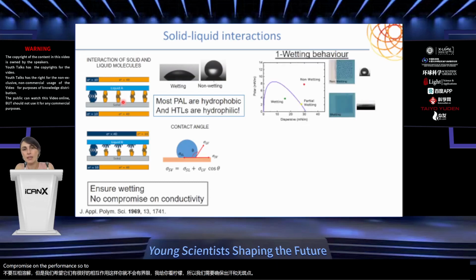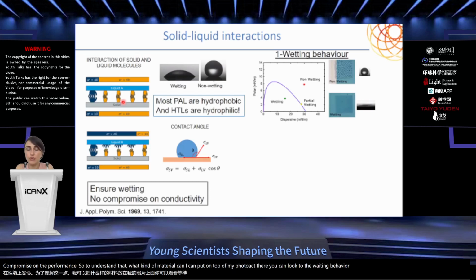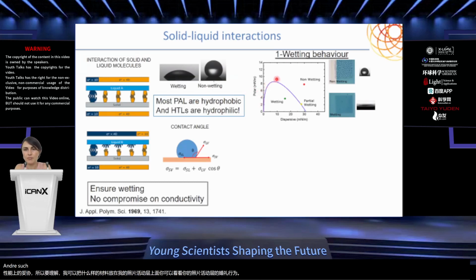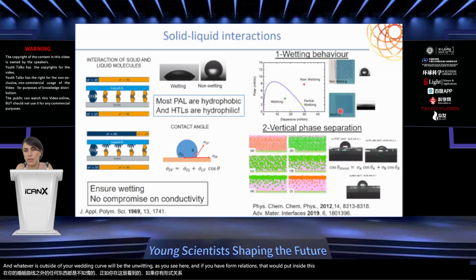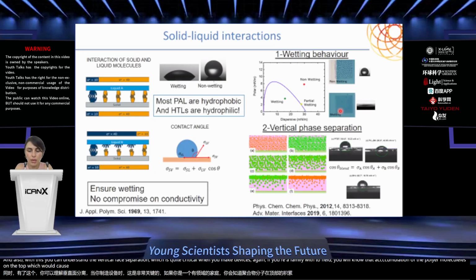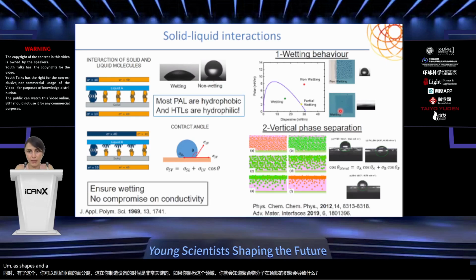So to understand what kind of material I can put on top of my photoactive layer, you can look at the wetting behavior of your photoactive layer and create such a wetting curve, so to say, using these polar and dispersive forces. And whatever is outside of your wetting curve will be the non-wetting, as you see here. And if you have formulations that would be put inside, this would be wetting. And also with this, you can understand the vertical phase separation, which is quite critical when you make devices. Again, if you're familiar with the field, you would know that accumulation of the polymer molecules on the top would cause you S shapes and lower fill factors.